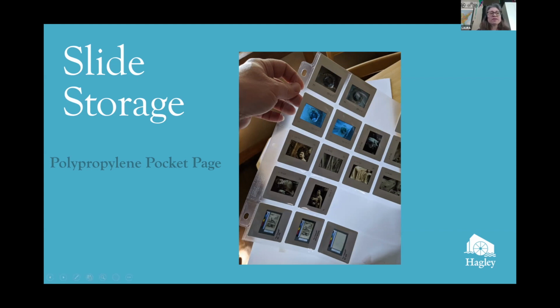The photographic activity test, also known as the PAT, is an aging test that can determine if a storage product will cause damage or deterioration to photographic materials. Be sure to look for paper materials that are acid-free, lignin-free, PAT tested, and passed. Opaque paperboard storage boxes are important to protect your collections from light. Do not use albums with self-adhesive or so-called magnetic style pages.